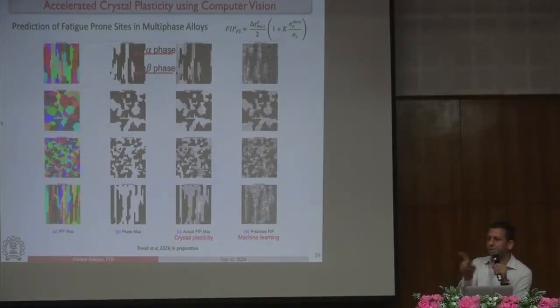Now, I don't need to run those 3 cycles of simulation. I show only this part, and I can predict which part of the microstructure is more prone to fatigue, not just the beta phase. Even in alpha phase, if there is heterogeneity and the alpha phase is surrounded by multiple beta grains, it will tell you that that is more prone, right?